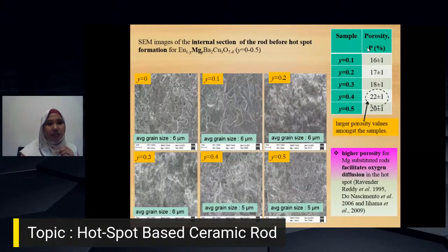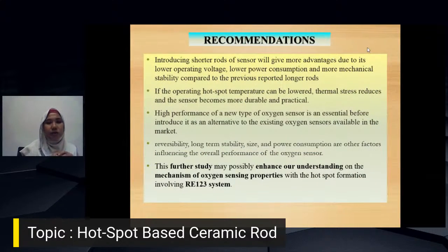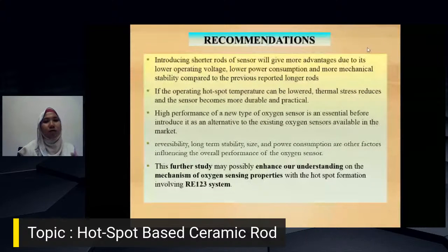So I would like to make a recommendation. You can see different types of substitution of the rare earth in the RE123, showing that the performance of the oxygen sensor can be improved. Actually this hotspot is a short rod. Introducing a shorter rod for the sensor will give more advantages due to its lower operating voltage, lower power consumption and more mechanical stability compared to the previously reported longer rods. If the operating hotspot temperature can be lower, thermal stress is reduced and it is more practical in industry.